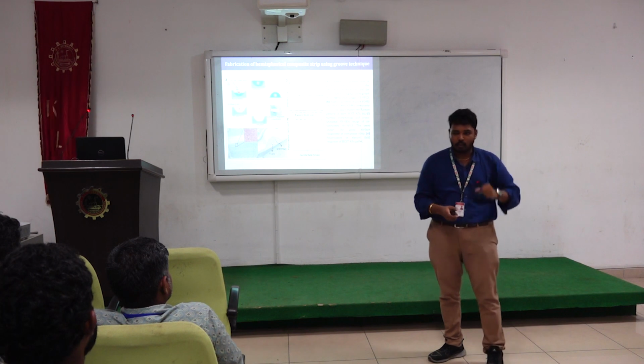Here what we do is make simple grooves in an acrylic sheet. We put titanium wire in the middle. The titanium wire itself will act as one of the electrodes there. The piezoelectric composite polymer was poured into that groove, and then we cured it. When I peel it out, a strip comes out with a thin titanium wire inside, which will be an electrode.